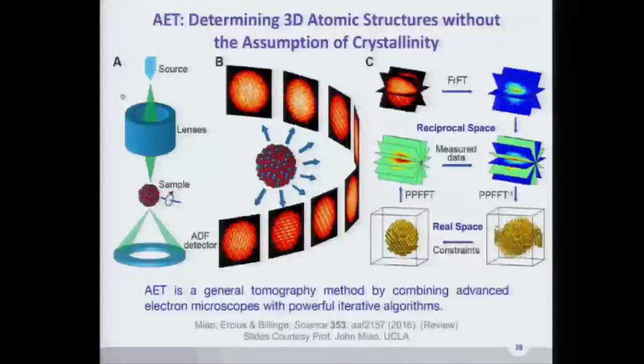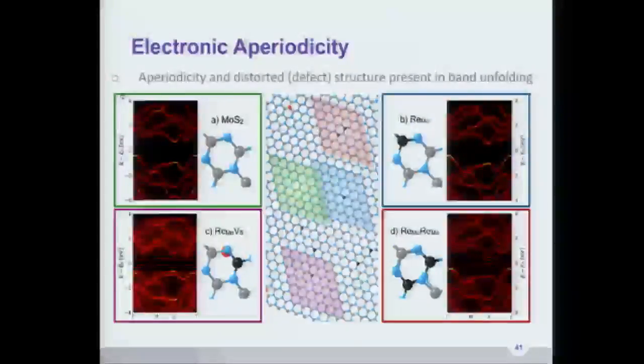So say I form a defect in theory, and I allow the system to relax, and I get a certain set of atomic coordinates, and they measure a certain set of atomic coordinates. Do those line up? And then from there, say, how do the properties differ if you use atomic coordinates from theory versus experiment? And how does the local disorder created in those, that they should be able to see, that maybe we don't capture, how would that change the behavior? I'm kind of giving the punchline away, but that's exactly what we see.